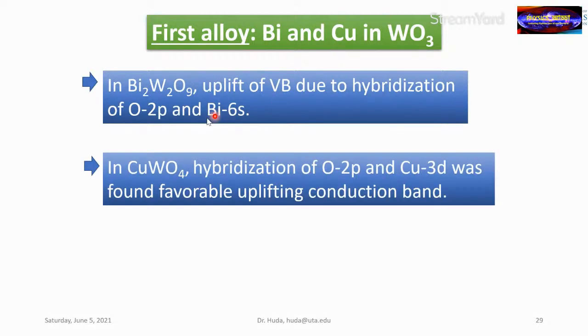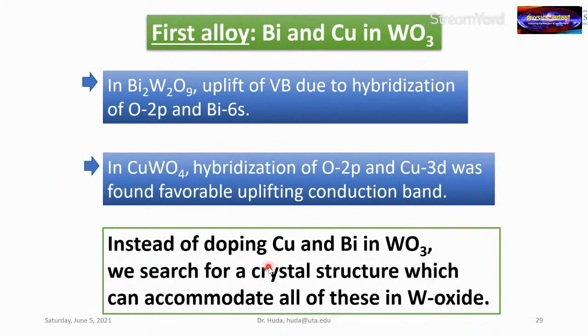Why copper? Because again, we found another material, copper tungstate, and we have seen that copper hybridizes with oxygen 2p and can uplift the conduction band. So what we decided is that if we use bismuth, it works on the valence band. If we use copper, it works on the conduction band, and both of these work via the oxygen 2p orbital. So instead of doping copper and bismuth in tungsten oxide, we will search for an alloy.